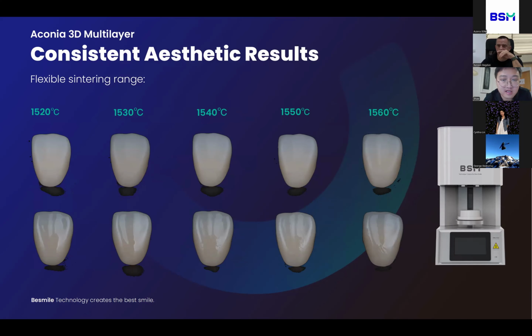So you can see that the shade is almost the same. The only difference is that if the temperature is a little bit higher, the translucency is better, but the shade always keeps the same. And our 3D Multilayer can support 3-hour fast sintering, including the cooling time.